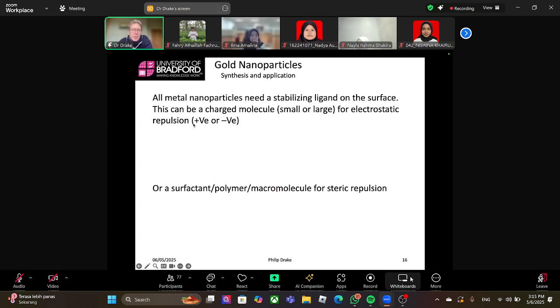There are three ways we can stabilize them. One is by positive charge, one is by negative charge. We take a nanoparticle and we put a positive charge on the surface. All the particles have a positive charge. When two particles come together, the positive charges repel each other and the particles don't stick together, they get repelled and they stay stable in solution. So positive charge stabilization. Equally, we could have negative charge stabilization. All the particles have a negative charge. Again, when two particles come together, the negative charges repel each other and you get repulsion.